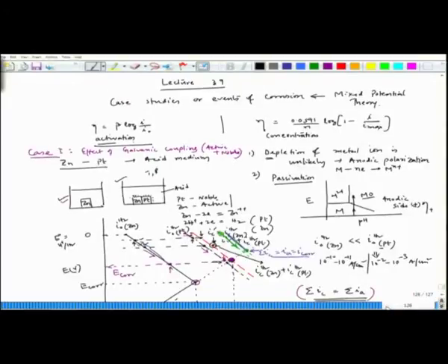And in fact the same effect was seen in this case also. You could see that when the platinum is connected, the hydrogen evolution rate on the zinc surface is reducing. So platinum is also acting as a depolarizer for hydrogen evolution on the zinc surface. So now we have seen two examples. Case 1, when we connect an active component with a noble component, and the second case, when we have the presence of a strong oxidizer. In both cases I could see that the corrosion rate of the active metal is increasing to a great extent. So let us stop here.